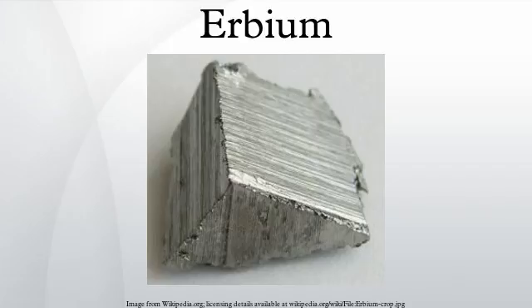Erbium's principal uses involve its pink-colored Er³⁺ ions, which have optical fluorescent properties particularly useful in certain laser applications. Erbium-doped glasses or crystals can be used as optical amplification media, where erbium ions are optically pumped at around 980 or 1480 nm and then radiate light at 1530 nm via stimulated emission. This process results in an unusually mechanically simple laser optical amplifier for signals transmitted by fiber optics.